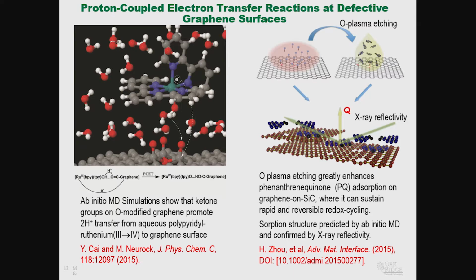In this example, our X-ray reflectivity folks found that plasma etching of graphene, of that single-layer graphene on silicon carbide, allowed things like phenanthrene quinone to strongly adsorb on the surface and yet still undergo redox reactions.